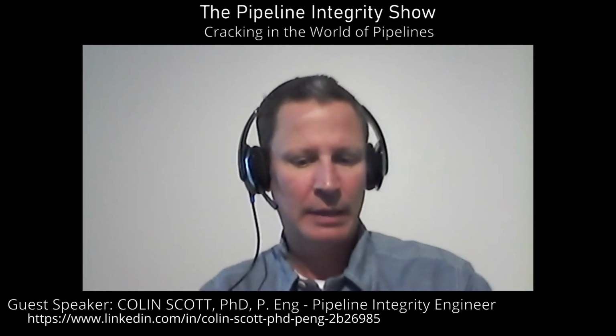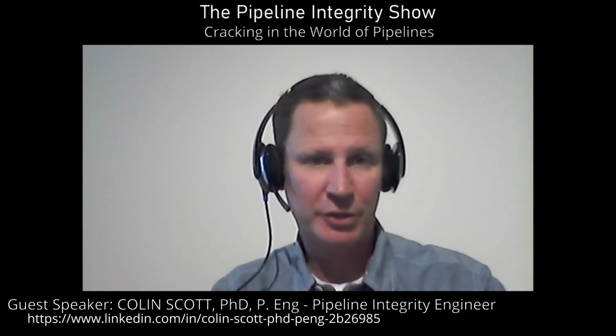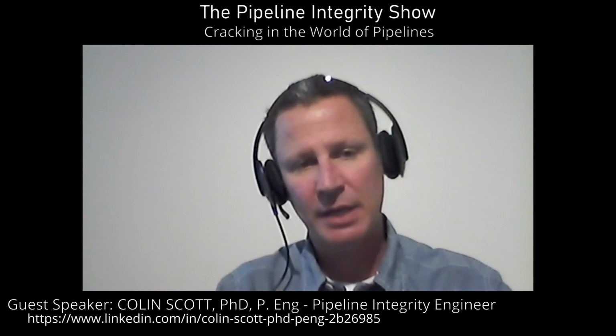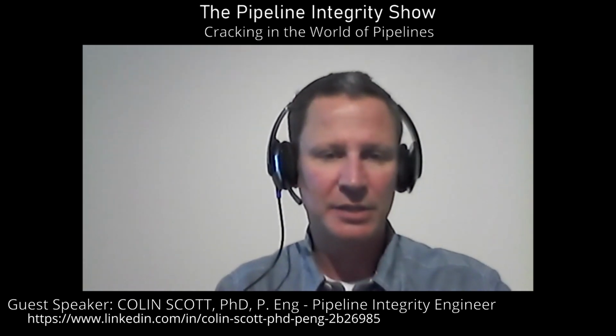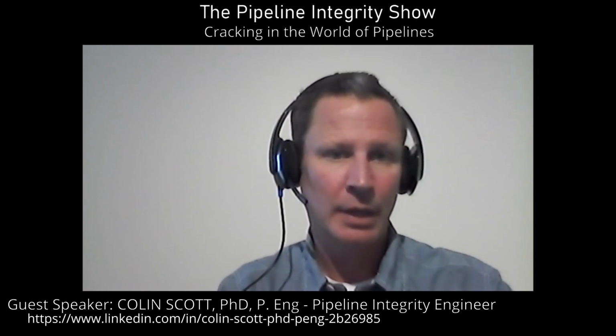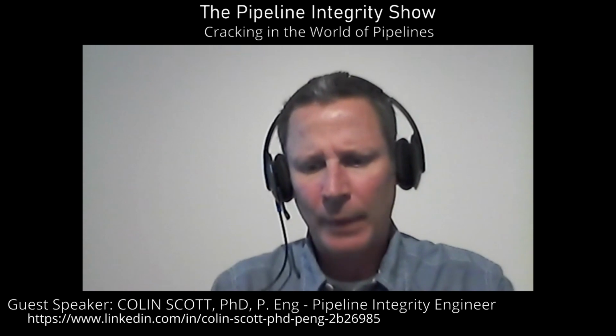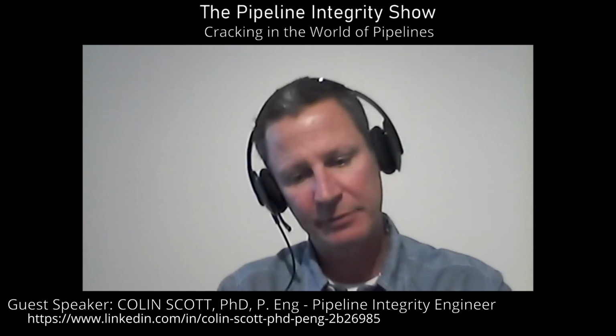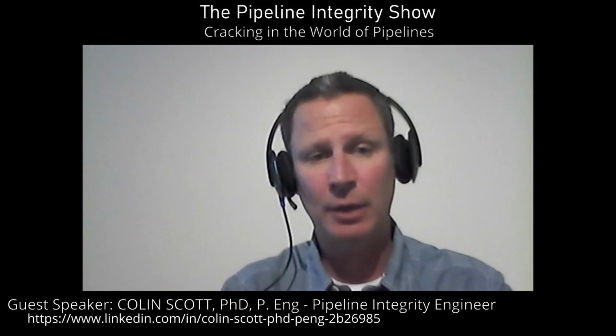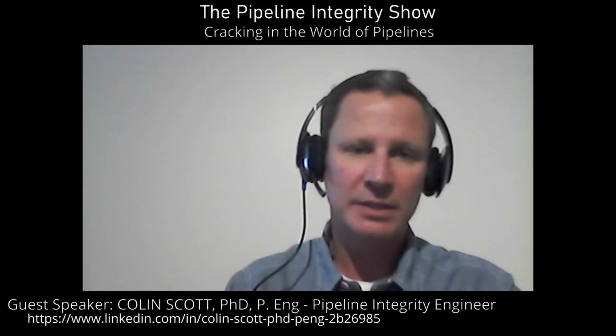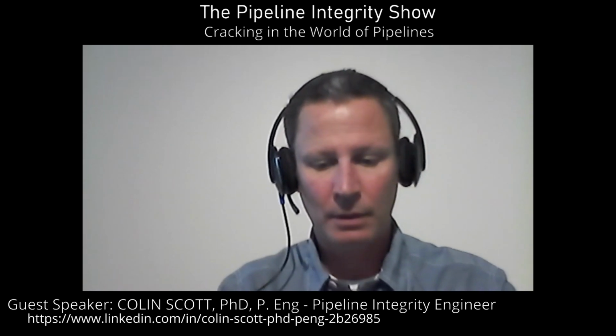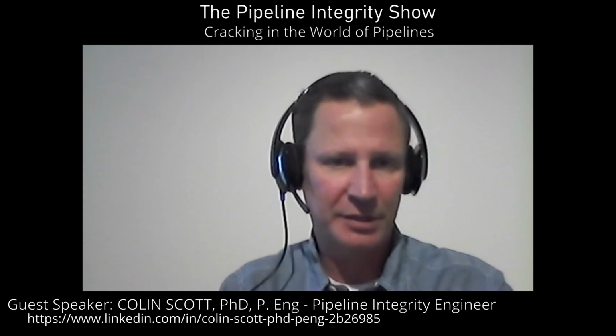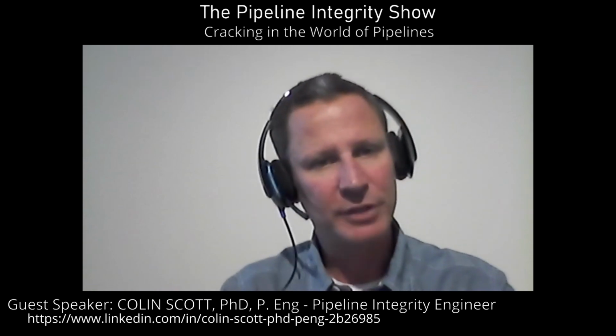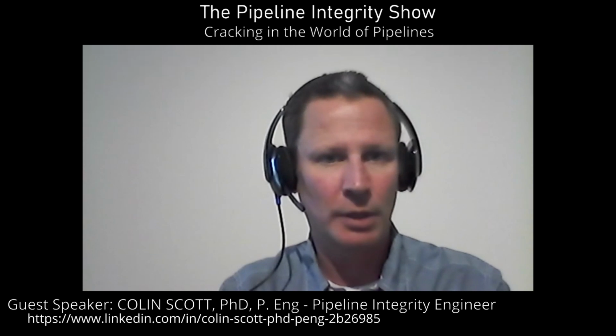Now, with fatigue, I mentioned that there's generally a cubic relationship with pressure cycling. If you do similar sorts of studies with stress corrosion cracking, the thinking is it tends to be not cubic, but a fairly linear relationship. So it turns into a different ballgame. What makes things particularly tricky for the gas people is that because the gas is compressible and they don't have quick ups and downs, their pressure cycling tends to be a lot slower. And stress corrosion cracking is sensitive to the speed of your pressure cycles. If you were to have a really quick pressure cycle, things would, for all intents and purposes, be fatigue. But once you do it slower, those corrosive mechanisms have more of a chance to take their time and do their chemistry and make things worse.